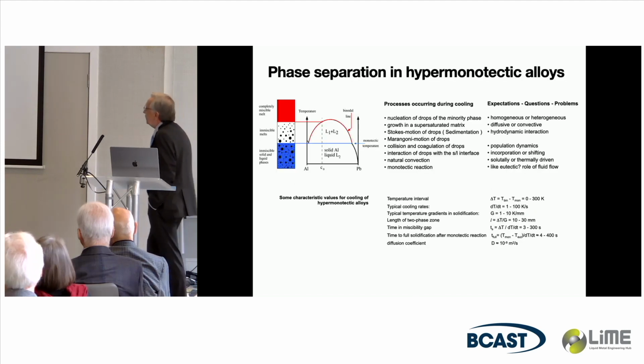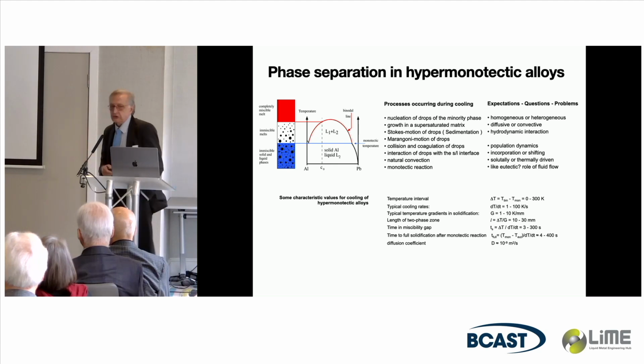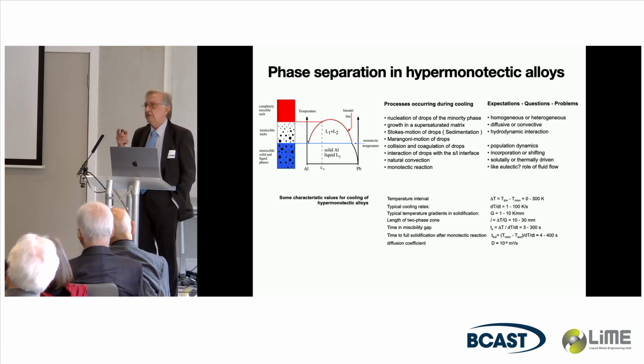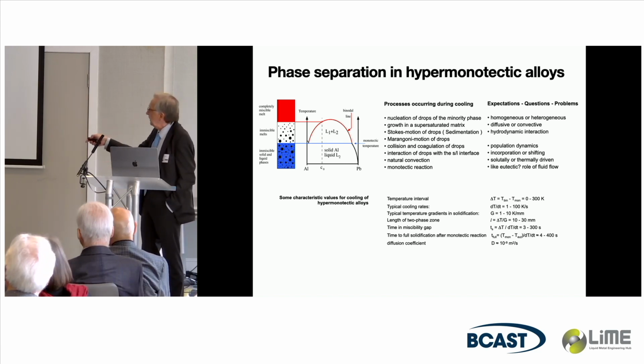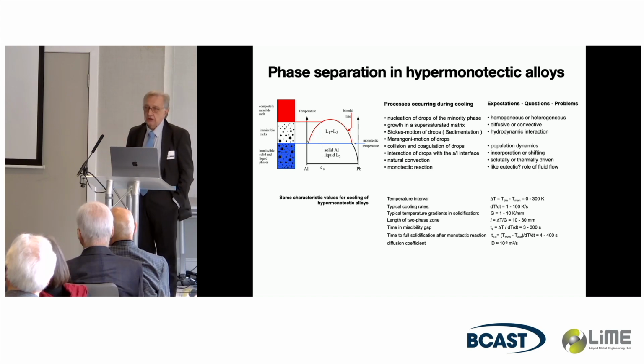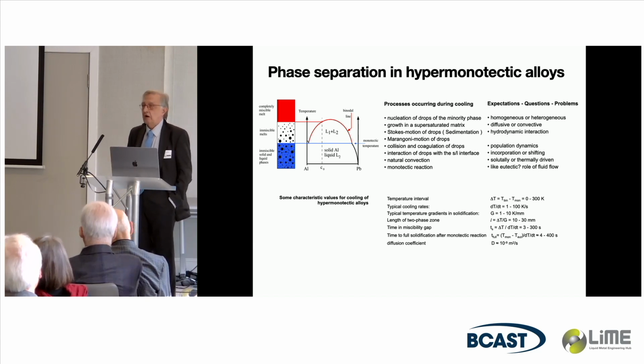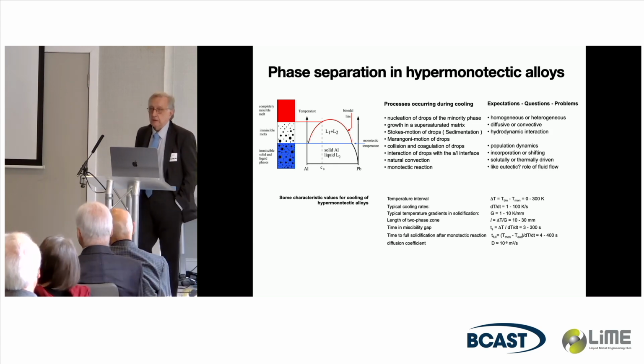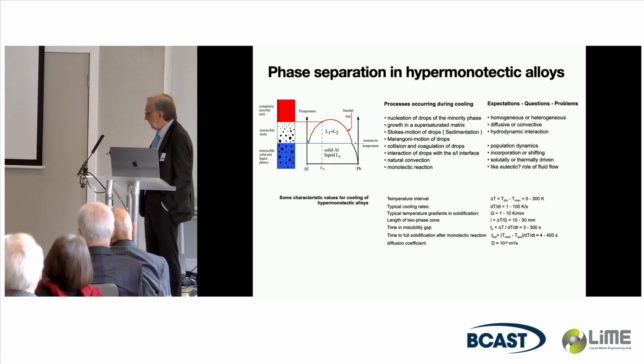So let me come to the important point of phase separation. The bad thing, if you have such a liquid miscibility gap, is between the critical point here and the monotectic reaction temperature. I'm not talking about this monotectic reaction because it's very similar to a eutectic with one essential difference. One of the phases is liquid. So you have a liquid-liquid interface, and in a gradient, this will induce interfacial convection and change the microstructure and change the well-known relations derived by Jackson-Hunt and by Tiller for eutectics. I'm not going to talk about that.